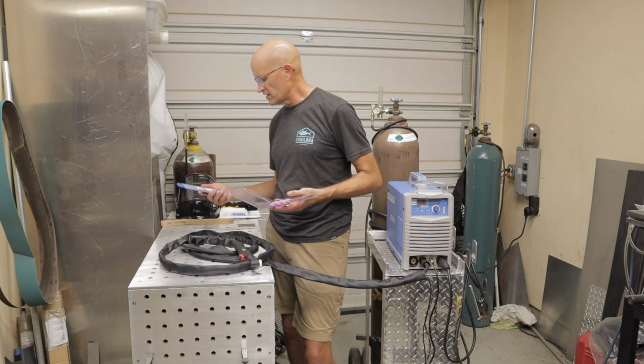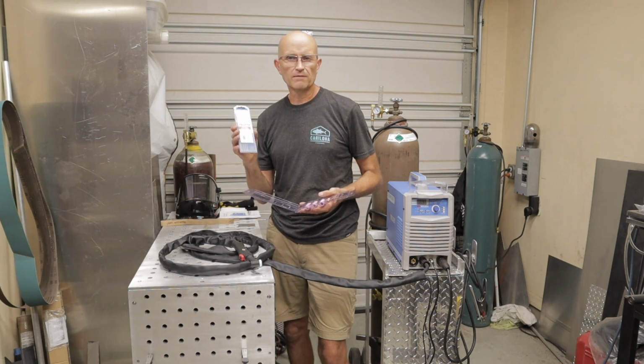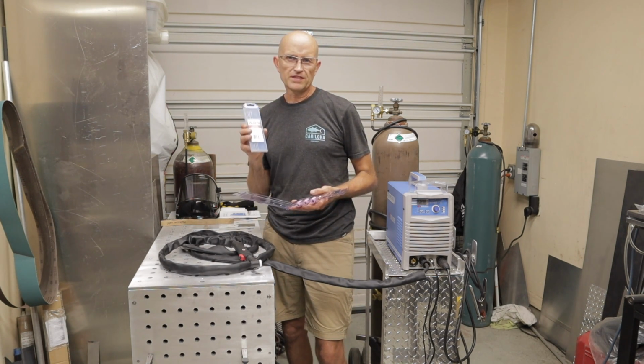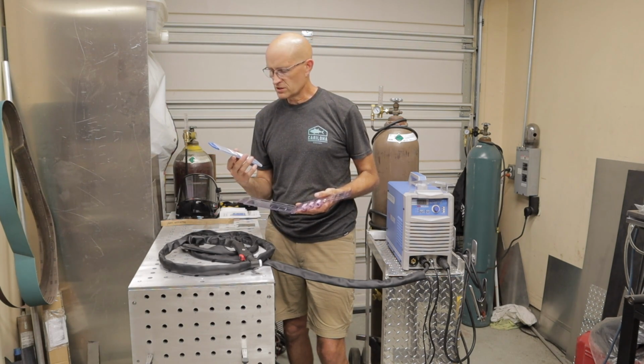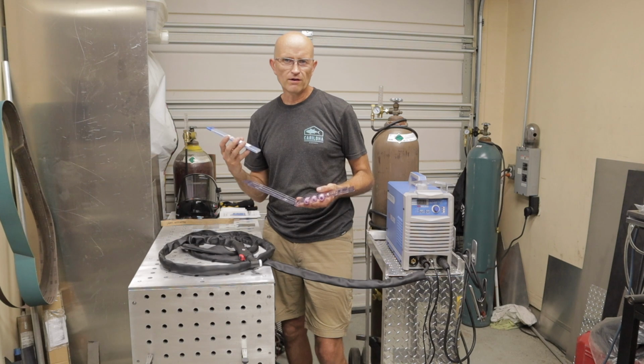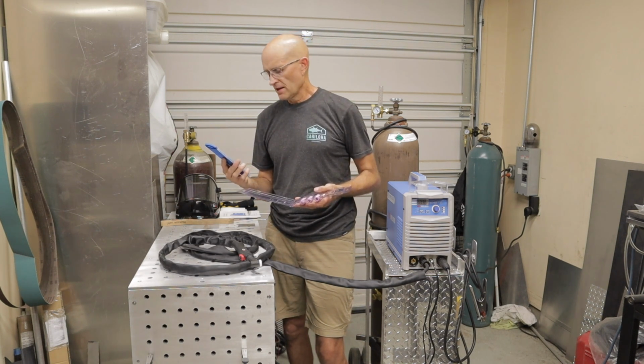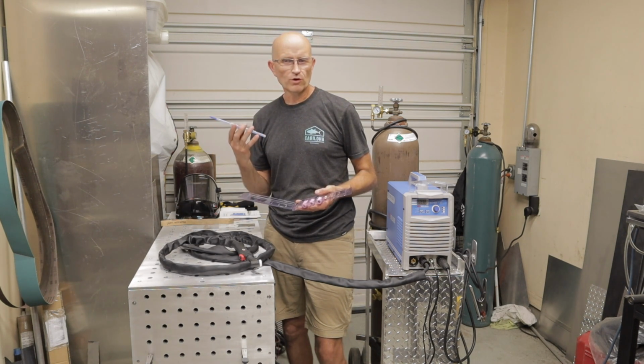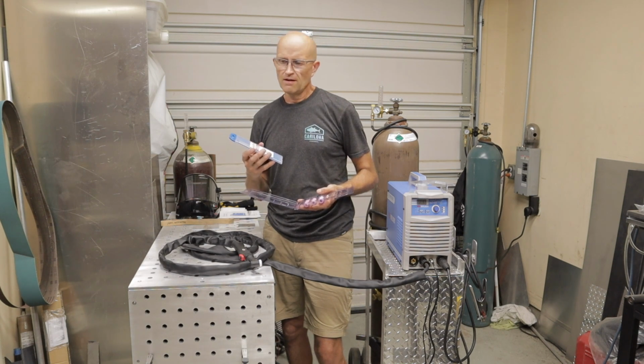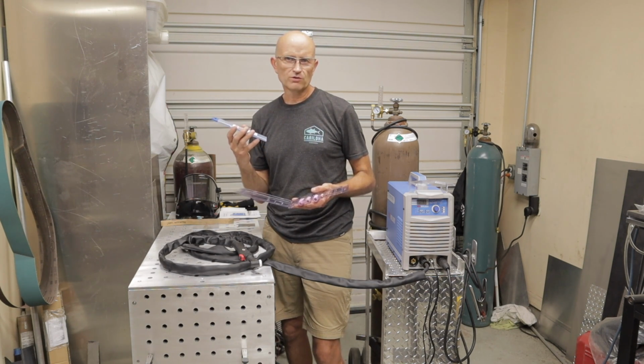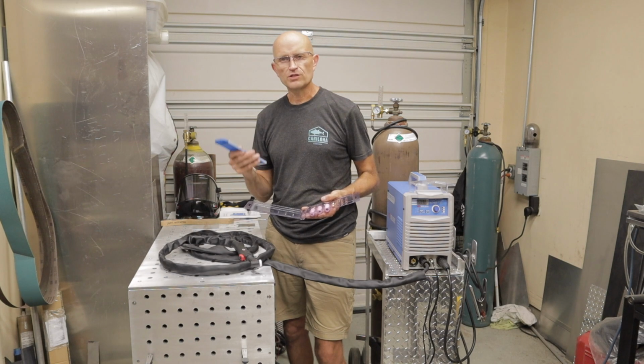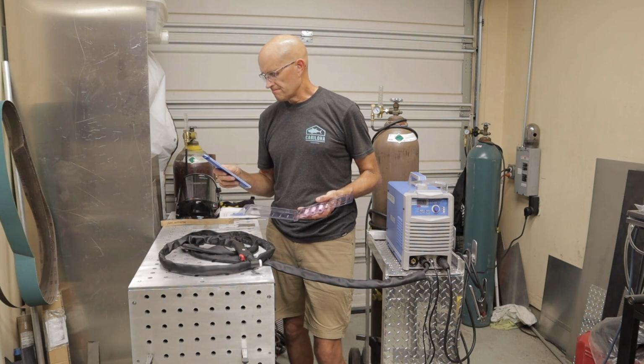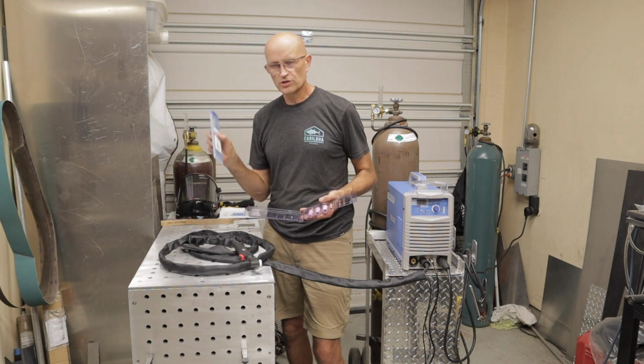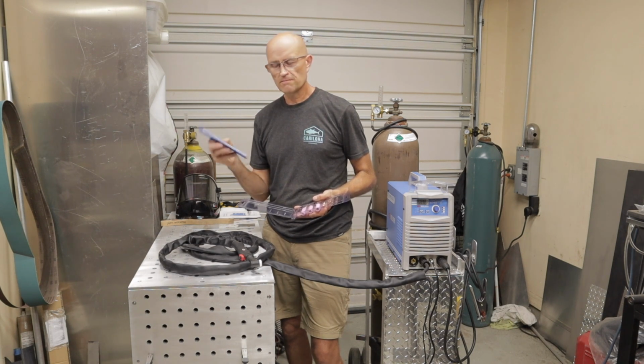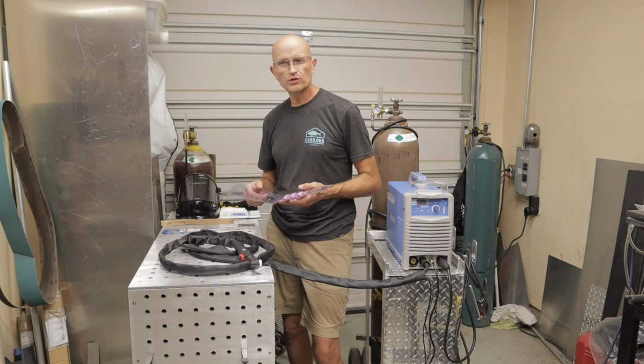And the tungsten that I use is 2% lanthanated tungsten. It's got the blue stripe on the top. It's the best I've found for all around TIG welding, and it works for aluminum, it works for steel, stainless, everything I've tried to weld with it, it welds great. So that's what I suggest. I usually start out with just a 3/32, and that's what we're going to do today.